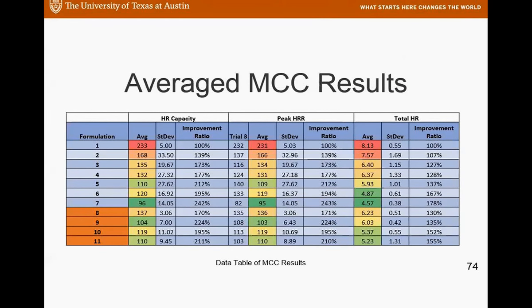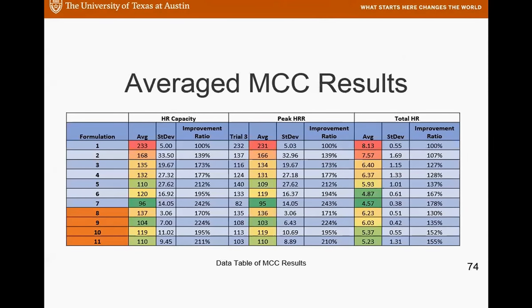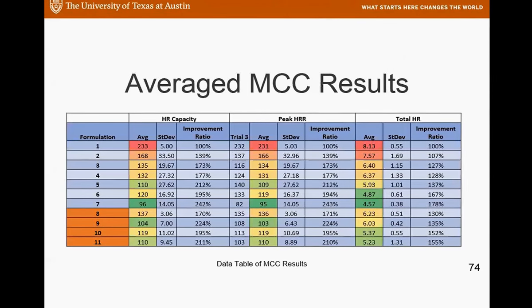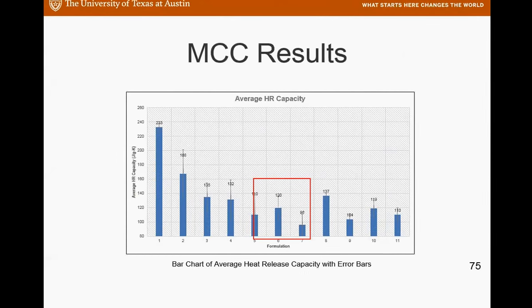The lower, the better for heat capacity, and then basically we look at all these formulations and compare all these data, and all these results have been sent to NASA to verify, to make sure that we have good data. Okay, so for MCC you have at least 3 repeatable runs. If it's not repeatable, you need 4. This is an ASTM standard. We did all these things and then compared, and that became a report sent to NASA.